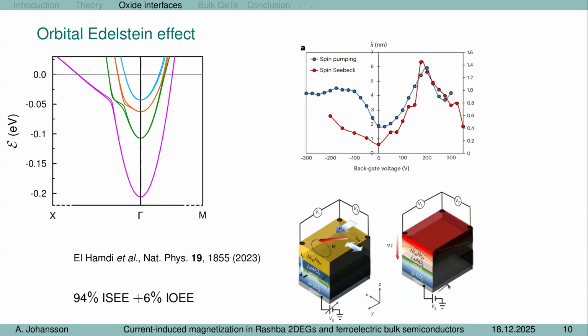And in this paper, they did some analysis with respect to the orientation of the system and compared that to theoretical calculations. And they found that the signal which they observe consists of spin and orbital contributions, and that the current which they inject, I think in this experiment, is like 94% of spin current and 6% of orbital current. So if this current is then converted into a charge current, it contains contributions from the inverse spin as well as inverse orbital Edelstein effect.